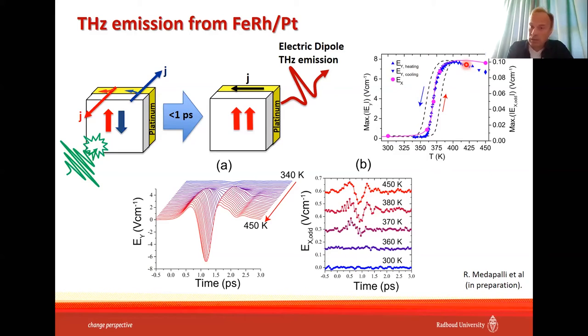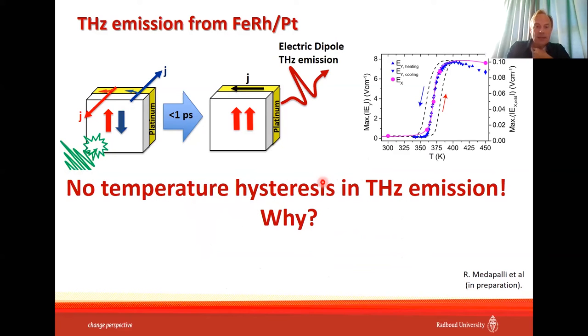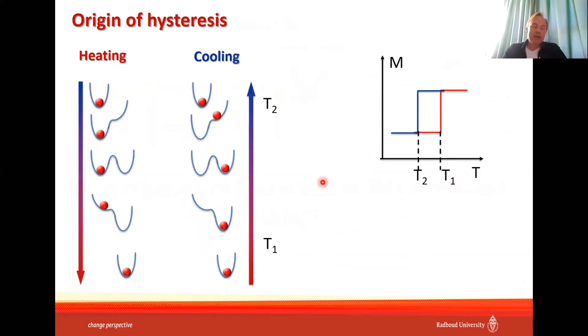This also, by the way, was one of the issues why the group of our colleagues who studied this effect before claimed that THz emission probes something else. Well, no temperature hysteresis in THz emission. Why? Let me remind you where the hysteresis comes from. If you have two phases, a high temperature phase and a low temperature phase, each of the phases I will represent by a minimum on the profile of the thermodynamic potential. It could be internal energy, it could be free energy. It doesn't matter in thermodynamics which thermodynamic potential you take.